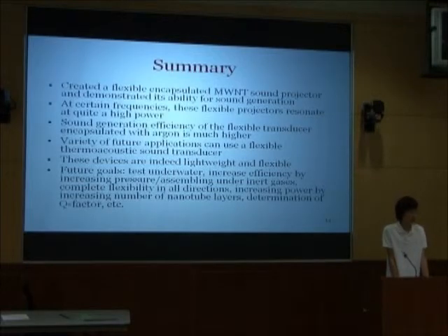Also, the sound generation efficiency of the transducer that was produced in argon is much higher than the other devices in just air. It's also flexible and lightweight. Even after we bent it a lot, it's a fairly stable signal.